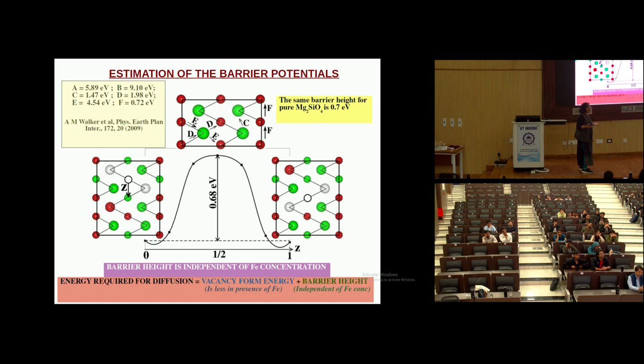Now, once the vacancy is formed, the vacancy has to migrate, it has to diffuse. And to diffuse, it has to overcome a barrier height. So it can diffuse in many different paths. We did all the calculations and we found that the vacancy wants to diffuse vertically in this crystal, as is shown here, and this is the diffusion barrier. So from here to there, this is the initial configuration and this is the final configuration, and they have to cross a barrier, and that barrier height we estimated. And we found that whether we have iron or no iron, this barrier height is kind of similar.